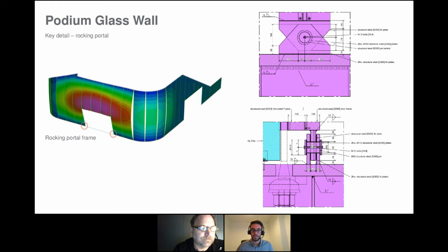So what we had to do was to develop a detail of a rocking portal frame. Basically the portal frame is hinged at the base and follows the glass facade and the cable and the rod, because it's basically restrained laterally against the adjacent rod. So the two rods running parallel to the portal frame are actually connected back to the portal frame columns. And therefore the portal frame follows the movement, reducing as much as possible the stress concentration all around the corner. Those are still there, but are much, much reduced compared to what we would have if the portal frame was fixed.